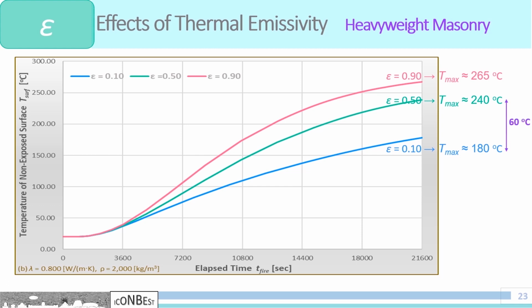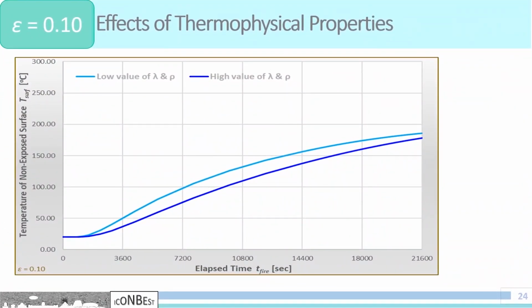It becomes apparent that the thermal behavior of a masonry wall sharply relies on the thermal emissivity of the clay material. This implies that the thermal effectiveness of low emissivity coatings is essential with respect to moderated heat fluxes through the geometry of the masonry wall. Therefore, brick units integrated with low E coatings are less prone to the engaged fire exposure. Following the findings presented previously, it becomes evident that the effect of the thermal emissivity in terms of heat wave propagation and temperature elevation is dominant. In this regard, the variation trend of temperatures with emissivity is straightforward.